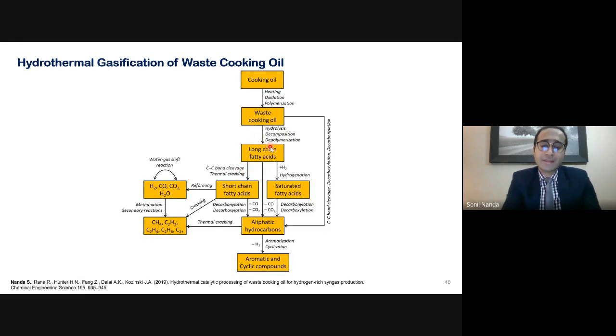different long-chain fatty acids. Now, these long-chain fatty acids act as precursors for autohydrolysis, carbon-carbon bond cleavage, thermal cracking, and hydrogenation reaction to produce different short-chain fatty acids and saturated fatty acids. Further, in the hydrothermal gasification, as a result of decarbonylation and decarboxylation, these short-chain fatty acids and saturated fatty acids will further break down to different aliphatic hydrocarbons. Further, these aliphatic hydrocarbons, as a result of aromatization and cyclization, produce different aromatic and cyclic compounds.